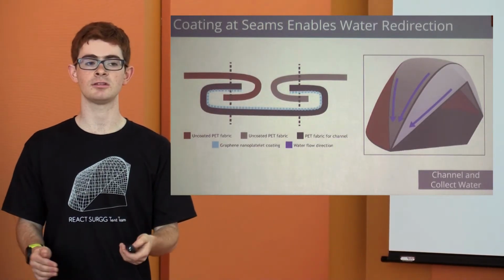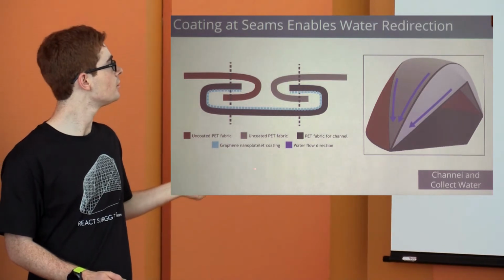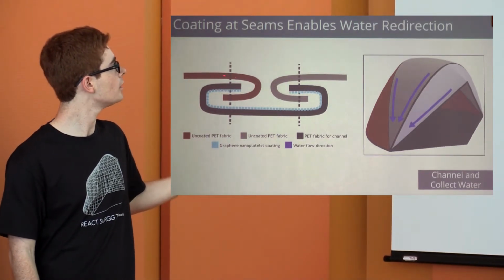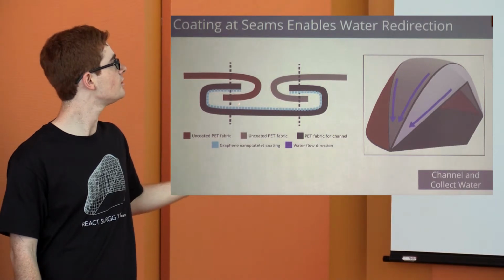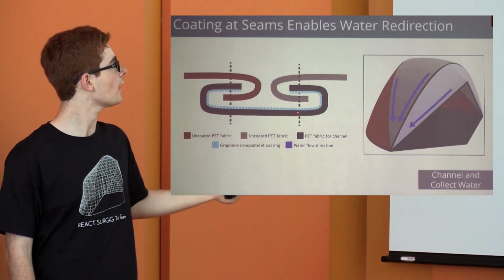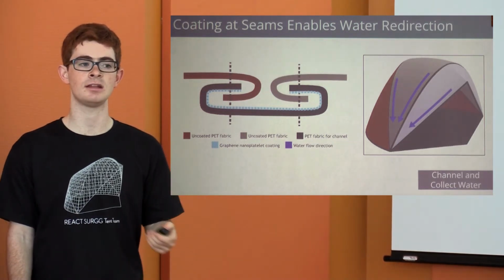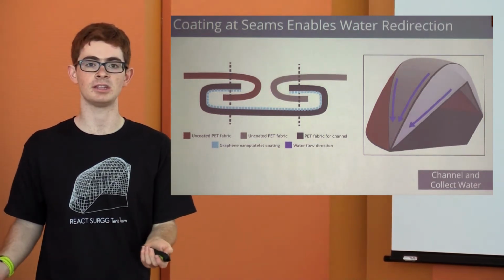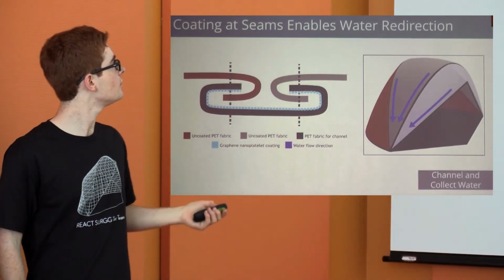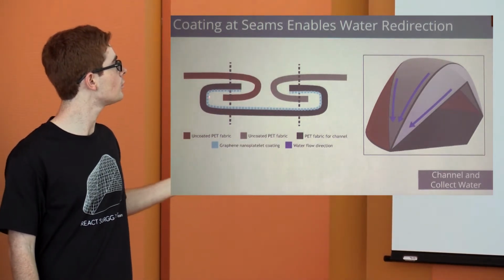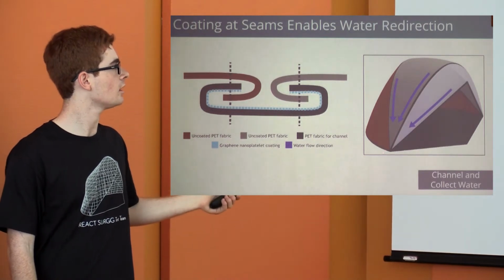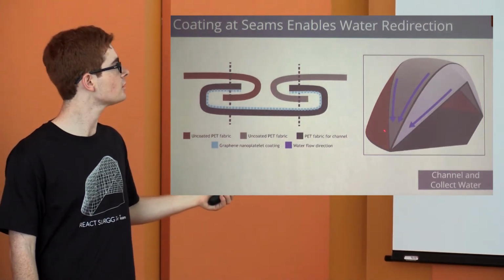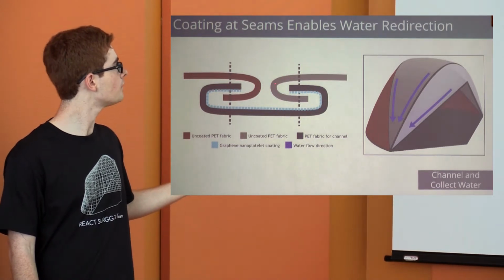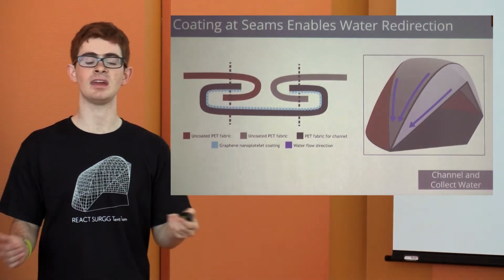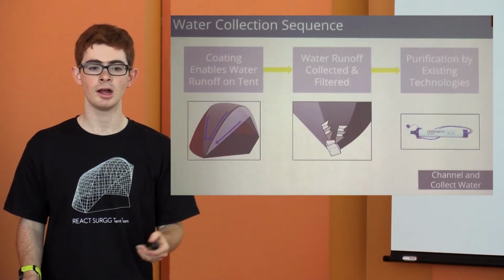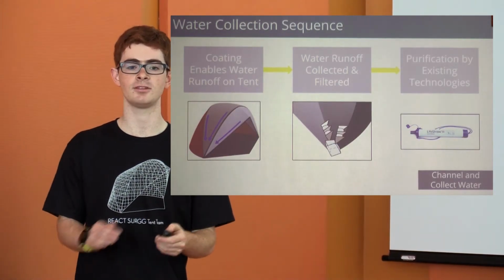So when we look at these coatings a little deeper in a cross section, the scheme works as follows. A piece of fabric, the red piece, is tucked in under. This dash line indicates sewing, and the black indicates the PET, which is 110 deniers. And denier is a measurement of fabric weave thickness or weave density. And this blue region is what's coated. So as water goes down the tent, following these blue lines based off the direction from the coating, water can drop down and hit the coating, and then it would just propagate down the tent into an area where it could be collected. So the coating would enable the water runoff to fall down the tent.